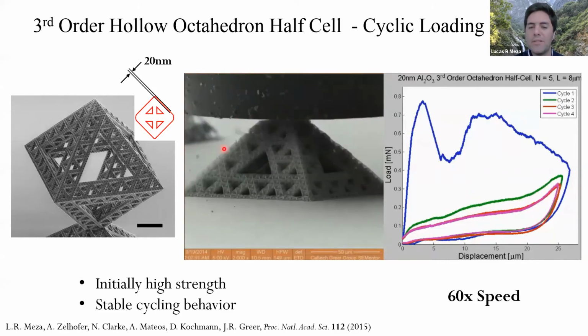So what this hierarchy buys you for this particular lattice is you're able to localize the failure more, to discrete beams in the structure instead of parts of the shell wall, and that inevitably gives you better recoverability because more of the node or more of the beam stays intact.